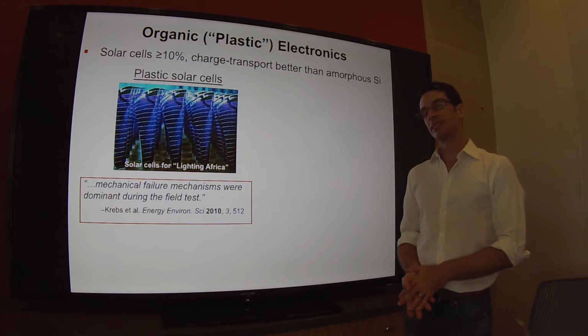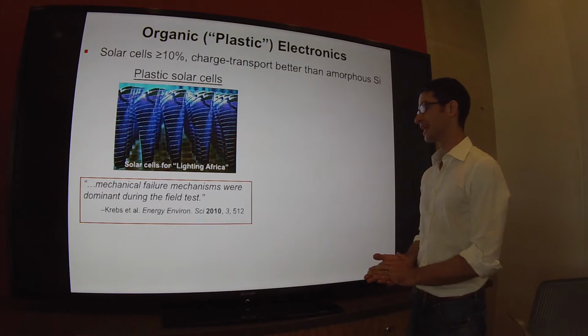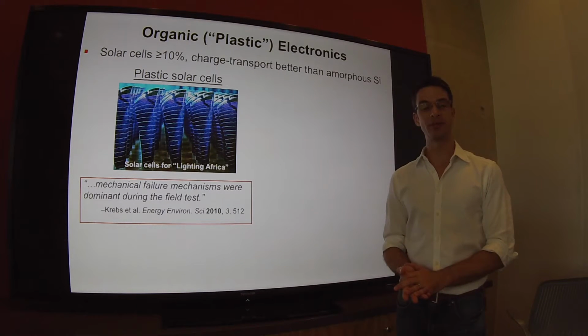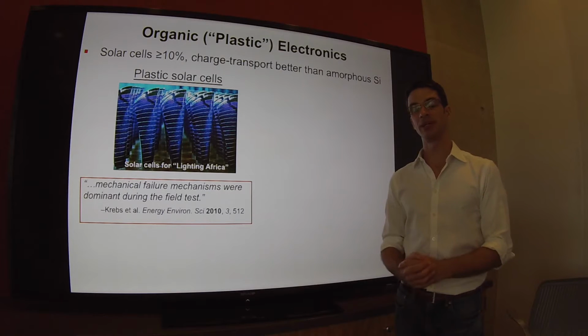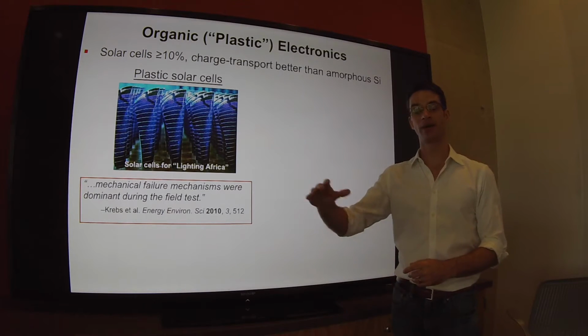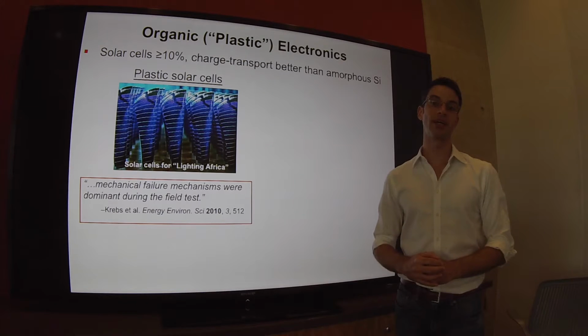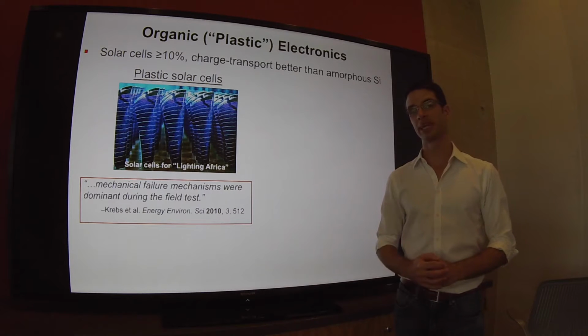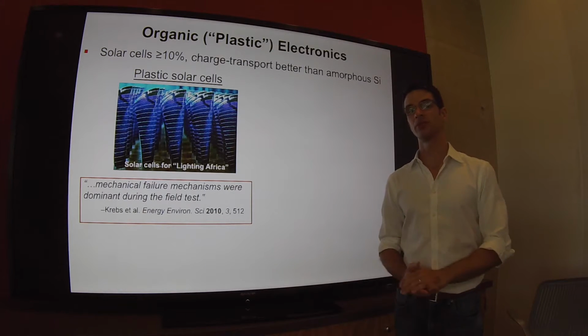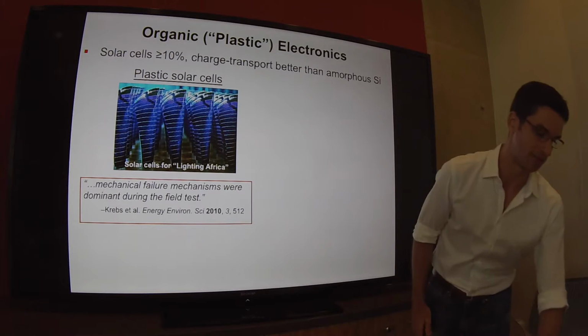The authors noted in this project, however, that mechanical failure mechanisms were dominant during the field test, and in the actual experiment where around a few hundred devices were deployed in rural Zambia, most of them that were returned to the researchers had evidence of mechanical failure.